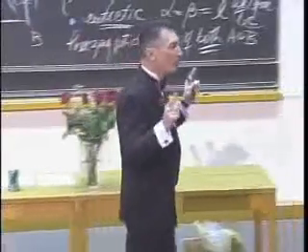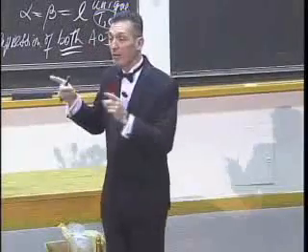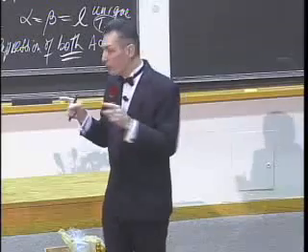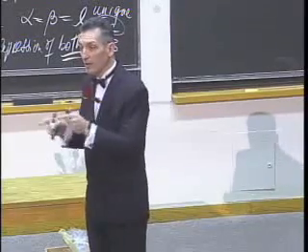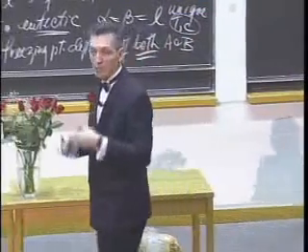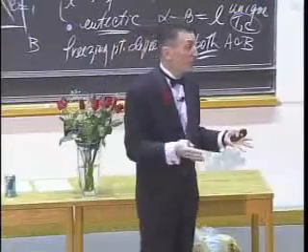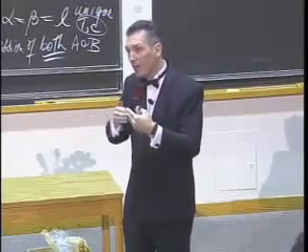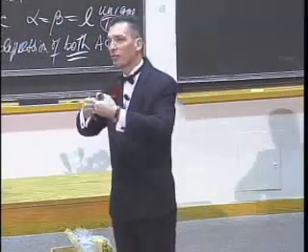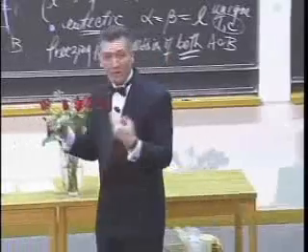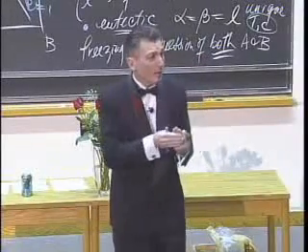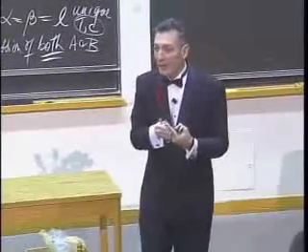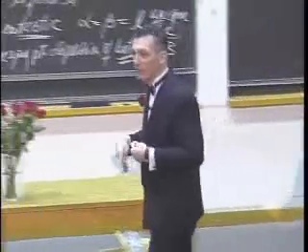In fact, when you design one of these large devices, you have in your design scheme a thermal budget. And you look at processing routes that consume less energy. Not only because you want to be energy efficient from a manufacturing standpoint, but because every time you put joules of energy in, you run the risk of having more and more diffusion. And those sharp PN junctions will become diffuse PN junctions. And as our feature size is getting smaller and smaller, the diffusion distances are shorter and shorter, and you've got less time before you've blurred those interfaces, and then the device is useless.